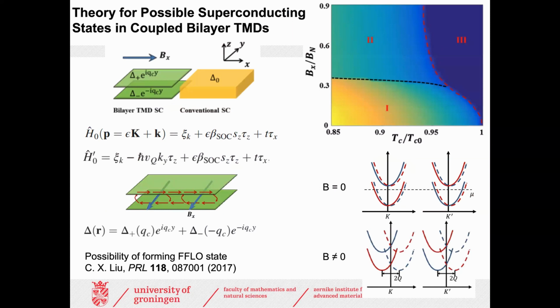So this comes with the theory of the possible superconducting state in a coupled bilayer TMD. We can use the moly disulfide as a model system. So the physics is the following: if you have a conventional superconductor, we have a uniform order parameter. But if we have a layer system, we have the order parameter that corresponds to individual layer. So we have order parameter to the top layer and to the bottom layer.